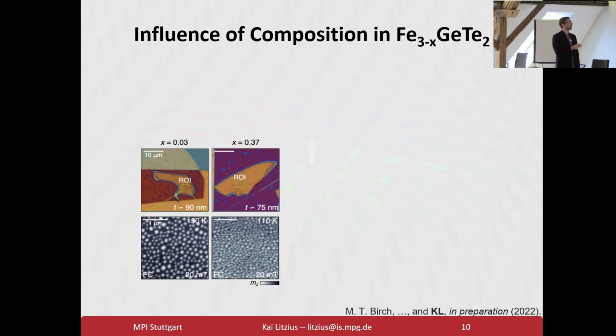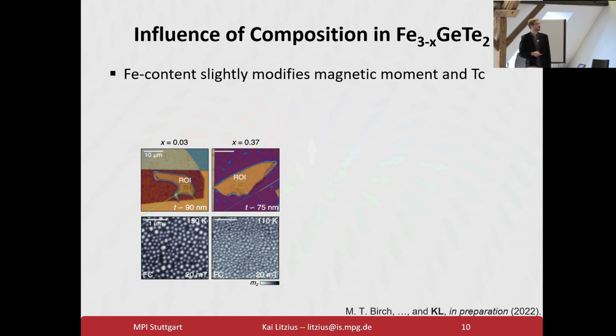For this, we have here essentially van der Waals Fe3-xGeTe2. So x=0 is Fe3GeTe2, and here we also have x equal to 0.37. So we have a lower iron composition. And that already changes the magnetic property quite significantly. Here we see, for example, a significant change in skyrmion density. And it also changes, for example, the magnetic moment and the Curie temperature, but not so much.